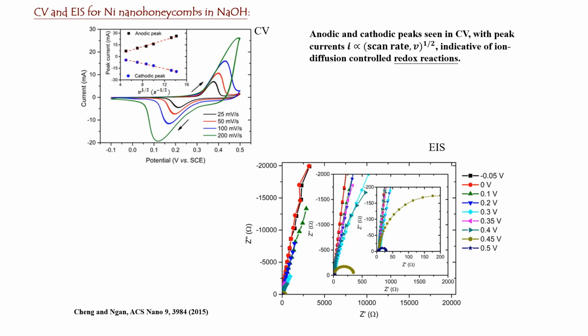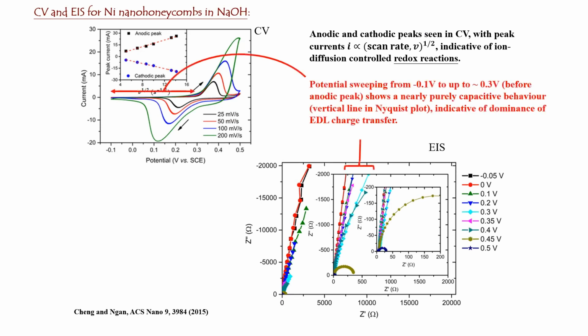And then this is EIS, okay? If you now scan your voltage, but as you scan your voltage, you avoid entering into the oxidation regime, so you just scan from here to there without kicking into the oxidation, the result would be a nearly vertical line in the complex number plot for the impedance. That also means that this is capacitance driven. From here to there, you don't have redox, you only have EDL.